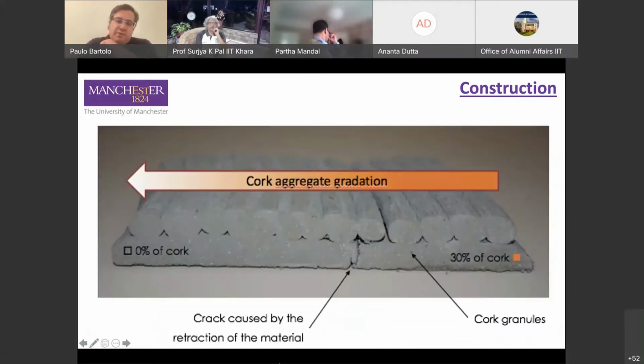This was one of the first structures that we produced. So we start with a composition of concrete and 30% of cork, and by the end we finish the printing process with 100% concrete. And this material change was created in real time without stopping the printing process. So, as I mentioned, this was one of the first structures.